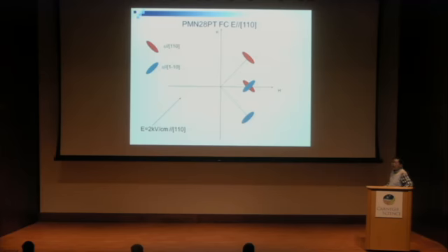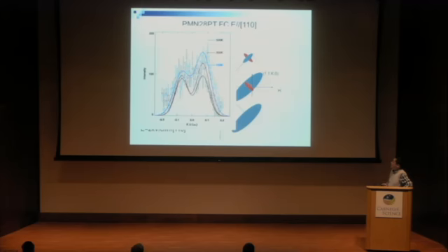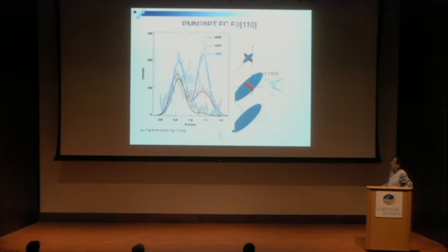And we did similar linear scans as before. Since we know from the mesh scan that the electric field seems to enhance the blue wing and suppress the red wing, the intensity looks like this. For the scan near the 100 Bragg peak, we see a clearly asymmetric two-peak pattern, and the right peak from the blue wing is clearly stronger than the peak from the red wing. And for the scan near the 110 Bragg peak, the weak peak from the blue wing is enhanced by the field, and at low temperature around 100 K, it's almost similar in intensity to the peak from the red wing.